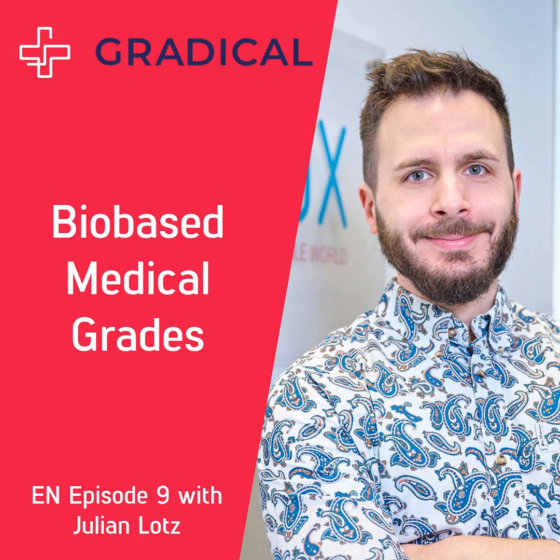Two thoughts on that. Of course, if you have a high carbon footprint in the beginning, then you can reduce greatly. We had a customer with a tube made from PTFE, and with some very elegant design work that they did on their device, we were able to switch towards a polymer blend of biopolyethylenes that we developed for them with some specific requirements. And they fell down from almost 30 kilograms of carbon emissions per kilo of tube to around cradle to gate minus 1 or something like that. So that's pretty nice. On the other hand, if you have polyethylene, for example, and substitute it with a biopolyethylene, you are saving greatly percentage-wise, but in the absolute numbers, it's not extremely high.